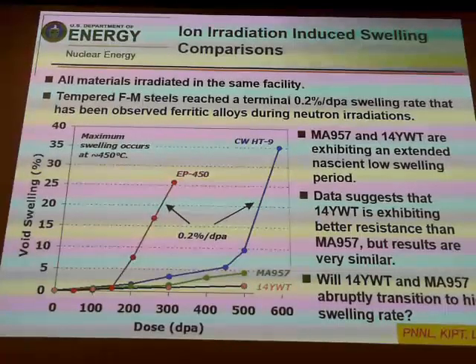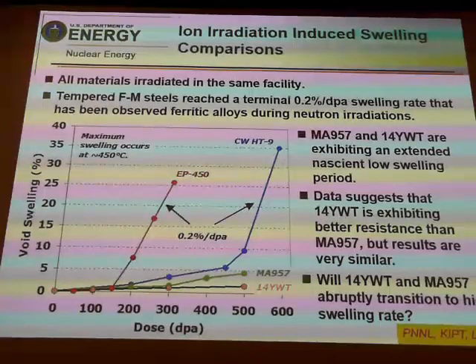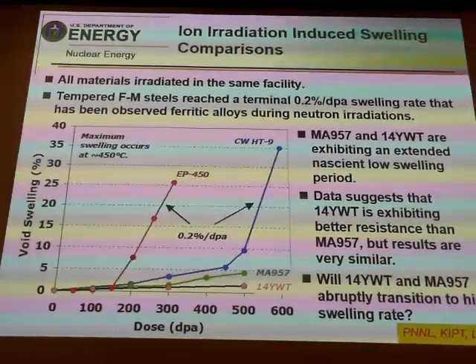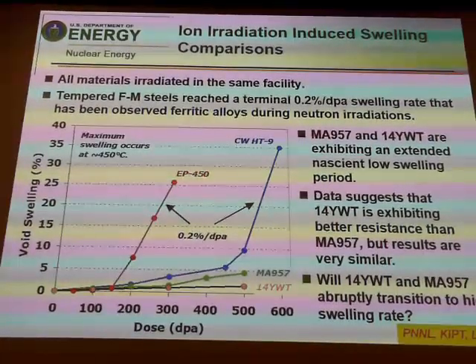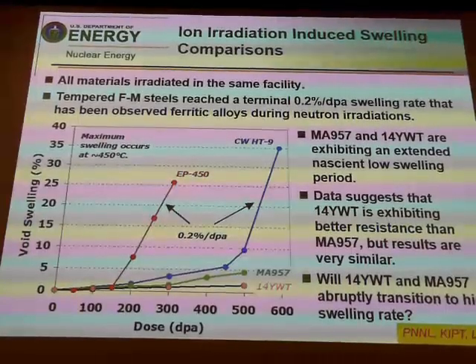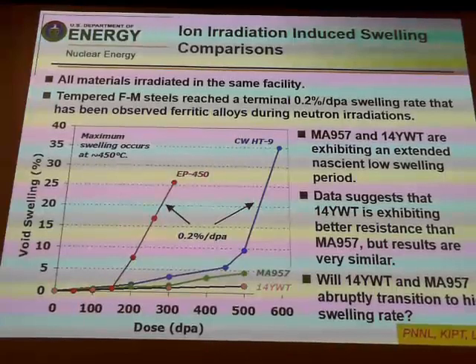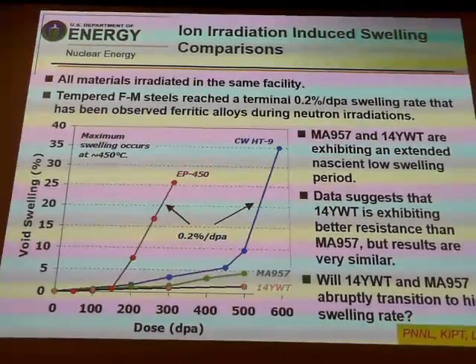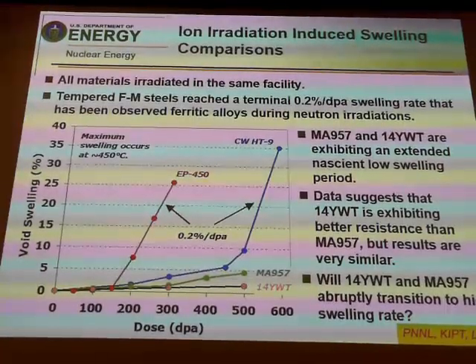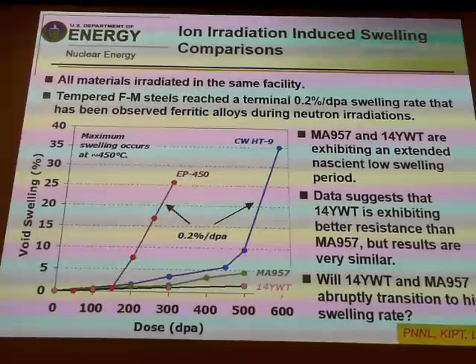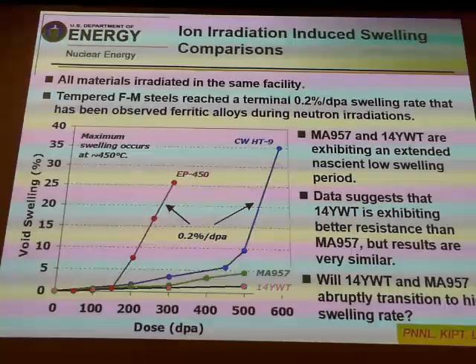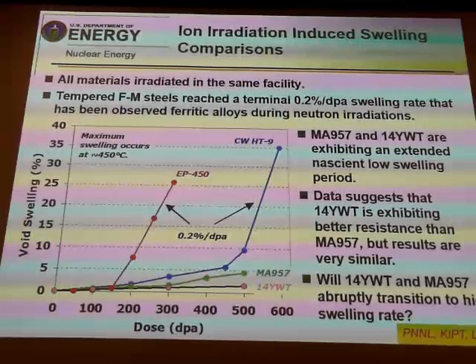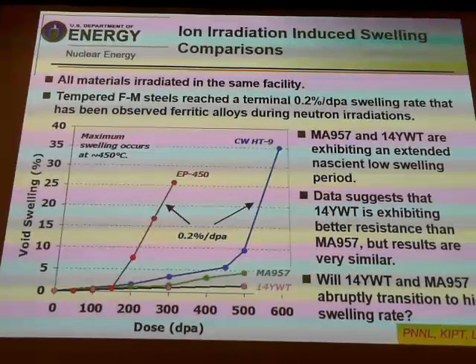It depends on what the reactor radiation temperature is, just like when we were talking about the difference between a fusion reactor and a fission reactor. Because the radiation temperatures in a fusion reactor range from 100 degrees C up to 1,000 degrees C, you run into a large number of different regimes where you can run into materials issues, from low temperature embrittlement to high temperature helium embrittlement above 600 degrees C. So when you start looking at other reactor concepts, it's not just dose that you need to look at when picking the right material for this application. You need to look at what temperature window the material is operating in.